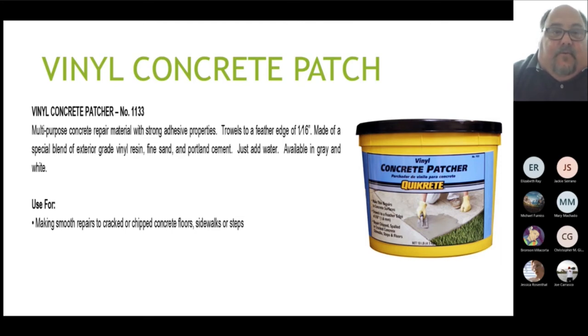Your surface prep for it is very simple. Just make sure there's no loose debris, make sure it's clean of dirt, paint, grease, oil, saps, things like that. Make sure it's damp, but no standing water when you apply this. Mix the material up, smooth it in, smooth it off, and walk away.